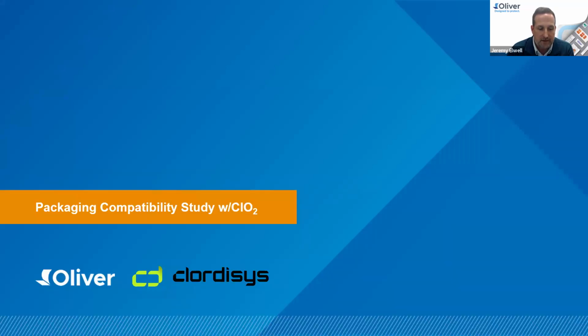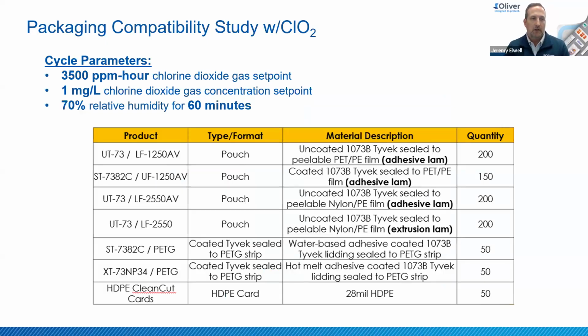So at Oliver, partnering with ClorDiSys, we have performed a packaging compatibility study, and we'll go into some of those results on the next slides. First one is just a summary showing the cycle parameters that we used at ClorDiSys, and then some of the material combinations and pouch type and format, meaning some were pouches, some were lid sealed to PETG strips. We also had high density polyethylene cards in this study. But some of the highlights in here, we talked a little bit earlier about adhesive lamination, extrusion lamination. So we want to point out that we did a combination of those, and moving forward, what we did see with some of these results.